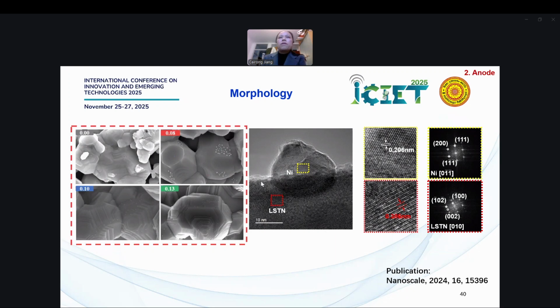So we tested the image. We find nickel exsolved on top of the main bulk titanate. So we see a bit of nickel growing on top, or even on the surface, of this particle. This sort of thing is shown in the image here on the left-hand side. These are all nickel. So nickel gives a good catalyst, not only in the lattice but, through the reduction operation, on the surface of the particle. So it gives a good catalytic activity.